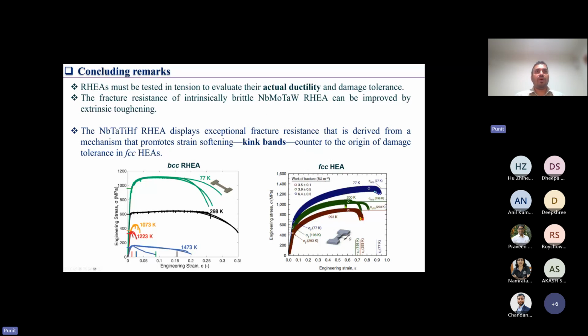The niobium, tantalum, titanium, hafnium refractory high entropy alloy is really interesting because it shows exceptional fracture resistance, which is derived from a mechanism which promotes strain softening. Kink band formation is a strain softening mechanism, and it gives you really high fracture toughness. And this is really opposite to what we see in FCC high entropy alloys, where you have extensive strain hardening, which resists the nucleation of microvoids and gives you high fracture resistance. In this case, you have a strain softening mechanism, kink band formation ahead of the crack tip, which is able to spread the damage away from the crack tip and give you a high fracture resistance.